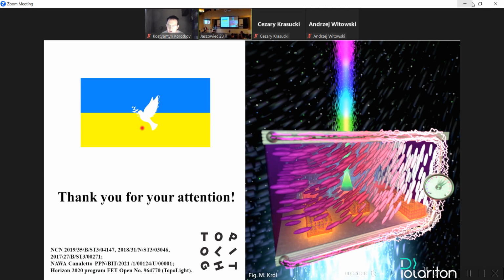So I would like to ask about the perovskite, because you said that you need fully inorganic perovskite for room temperature condensation. Is it because of the degradation of hybrid perovskites under excitation of laser? And do you face this problem with your fully inorganic perovskite too during condensation? So is condensation repeatable for the same place on the sample?